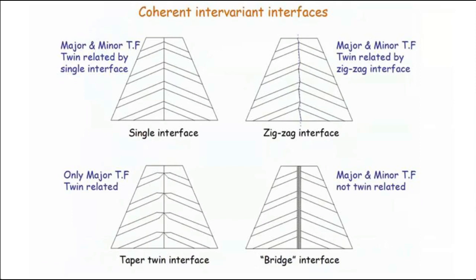Now just imagine, that's the most difficult case. If you have two nickel titanium orientational variants coming next to each other, the ideal and the best condition is that whatever we have spoken earlier on, this condition that you have to have a twin interface, comes right away. It's a great coincidence that it comes right away, and one single interface twin relates both of them. Now that's the best, and that's among the wish list of what we want. So it does happen that in some of the variants you have such a situation where a single interface can twin relate both the major and minor twin fraction.